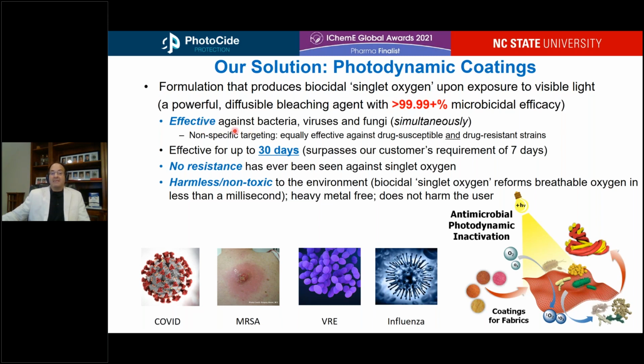It's simultaneously effective against bacteria, viruses, and fungi, but because it operates in a similar fashion as bleach, the non-specific targeting means that it's going to be equally effective against drug susceptible and drug resistant strains. Because it's non-specific, that also means that no resistance will arise to these reactive oxygen species, such as singlet oxygen, and that our formulations are effective for up to 30 days.